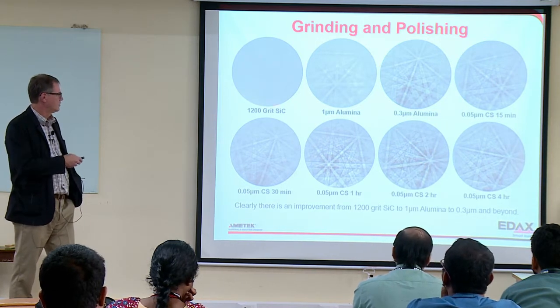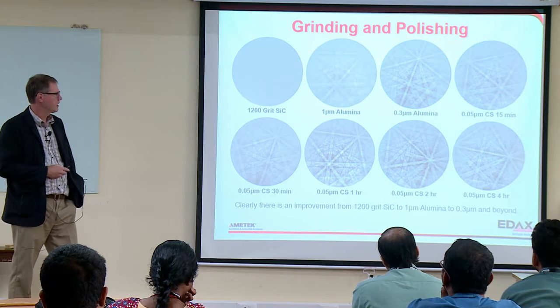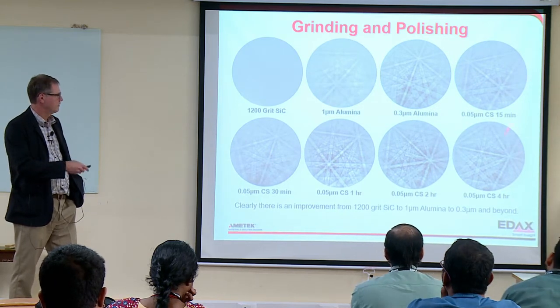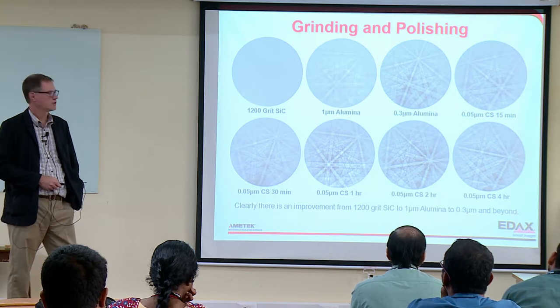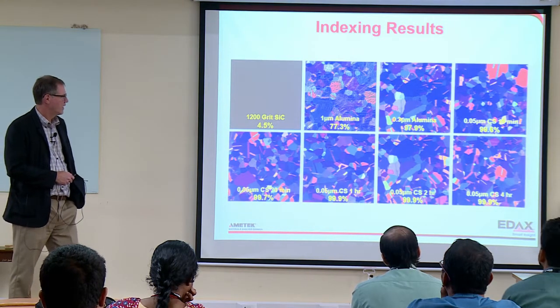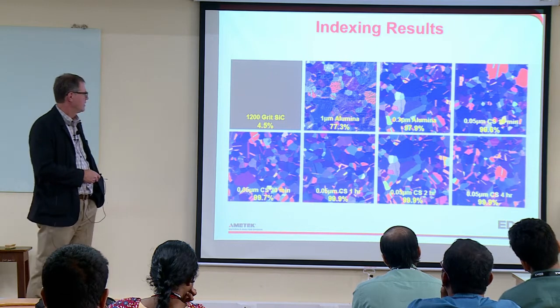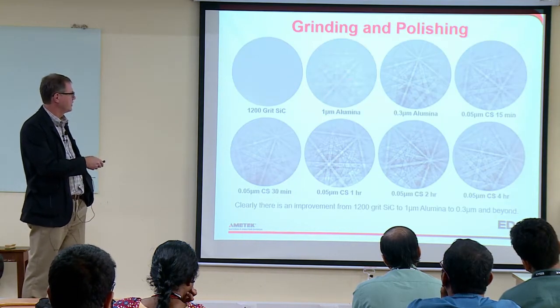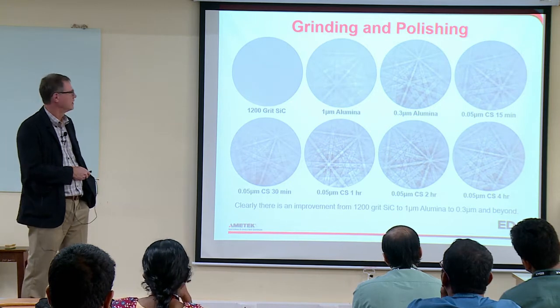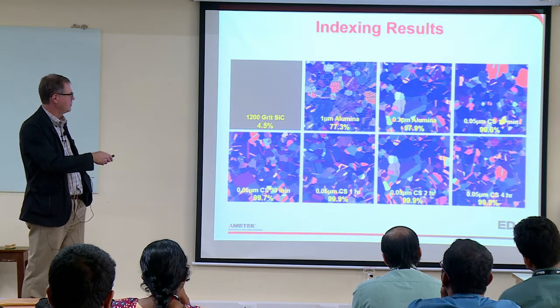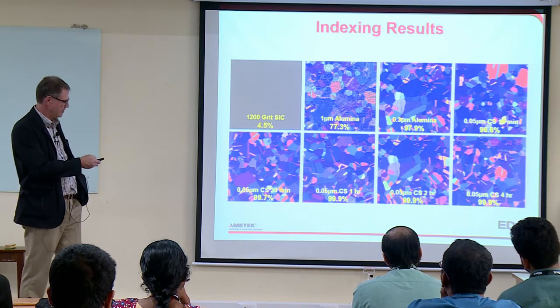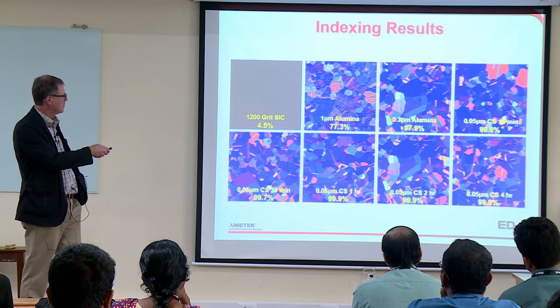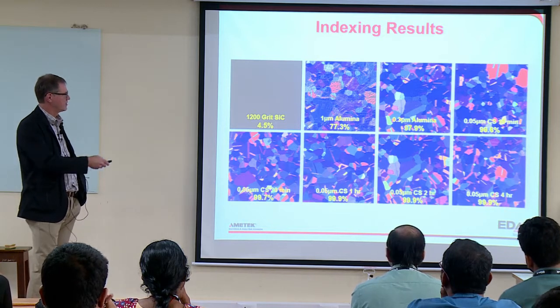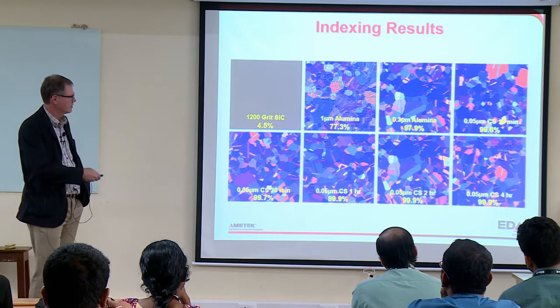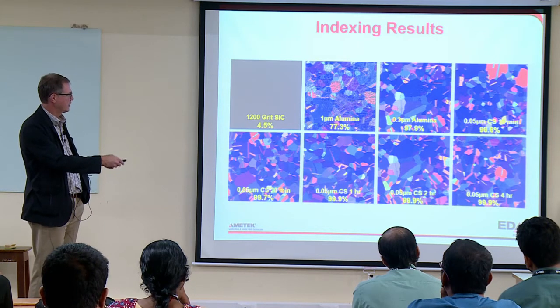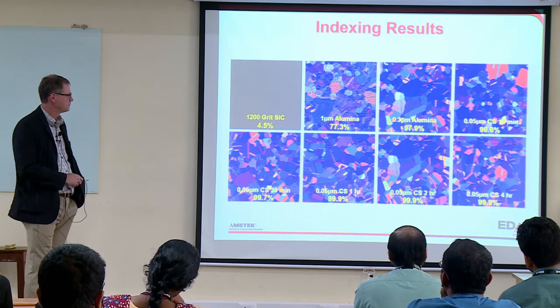But we typically do, go through all the basic polishing steps, including alumina, and then we usually finish with this colloidal silica on a vibratory polisher. Now there's other ways to do that, and I think I have a few slides on that. Now, even this pattern looks good, but we've picked the best pattern off the sample we could find. If you actually were to try to do a scan, you can see that there's still evidence of scratches in the material and some pores. And so it really makes sense to go to a better polish. And you can see I get really nice improvement once I get out here and do the colloidal silica step.